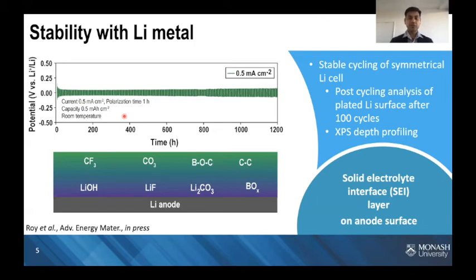I was more interested in exploring its interfacial properties. So after 200 hours or 100 cycles, I opened one of these cells and looked at the plated lithium surface by XPS depth profiling analysis. What I found is that on the lithium surface, there's a rich formation of fluoroalkyl groups. However, after etching, I found more inorganic species such as lithium fluoride and lithium carbonates, which suggests that this salt is able to form an SEI on the lithium surface, which includes both organic and inorganic species. This behavior is highly desirable for any electrolyte compatible with lithium metal anode.